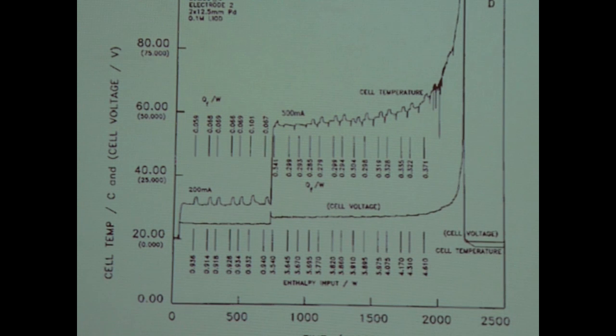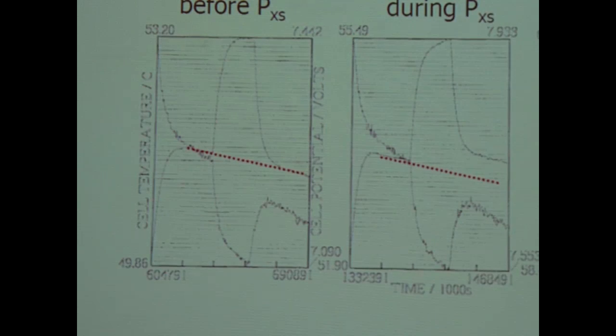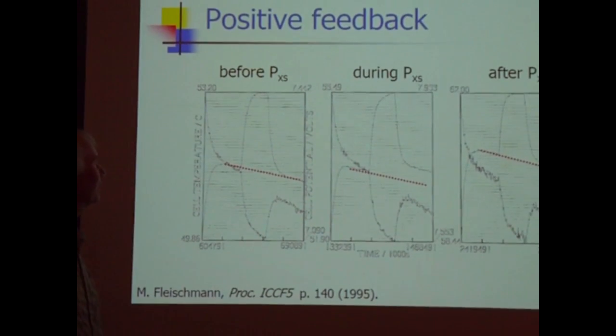For example, to do a good measurement, maybe you want to work at constant temperature. If you work at constant temperature, if your temperature is low, you can load well, but your excess heat's no good. If constant temperature is high, you can't load very well, but if you do get loading, you get the temperature enhancement for the excess heat. So let's look at what Fleischmann was looking at in detail.